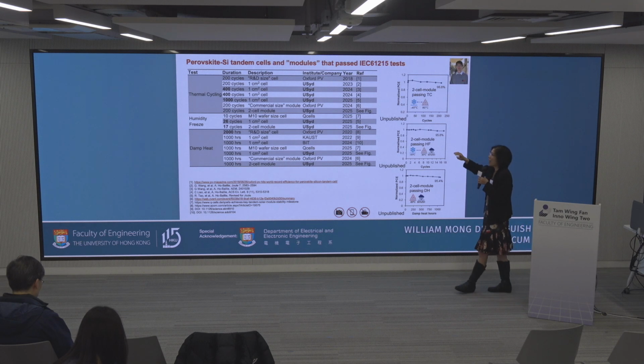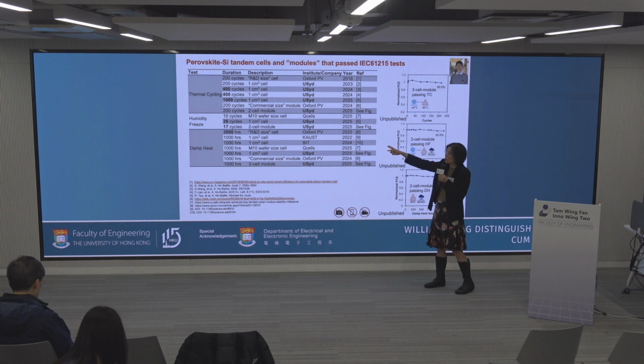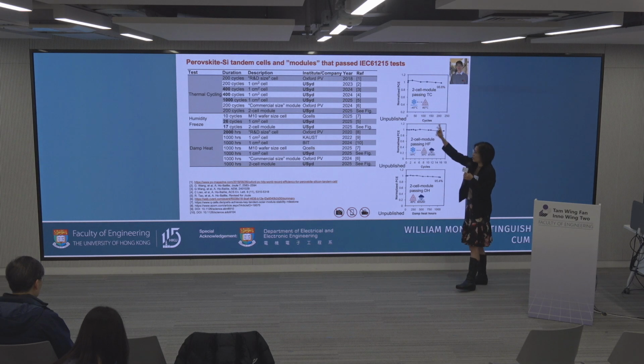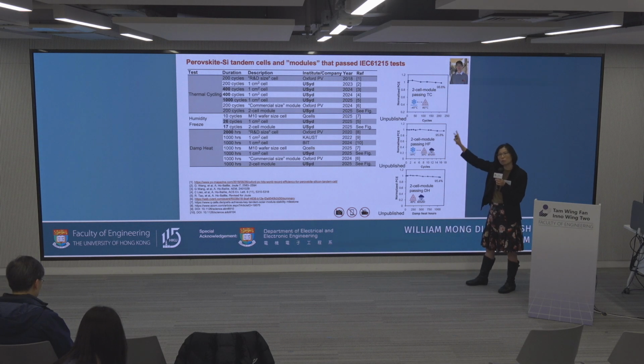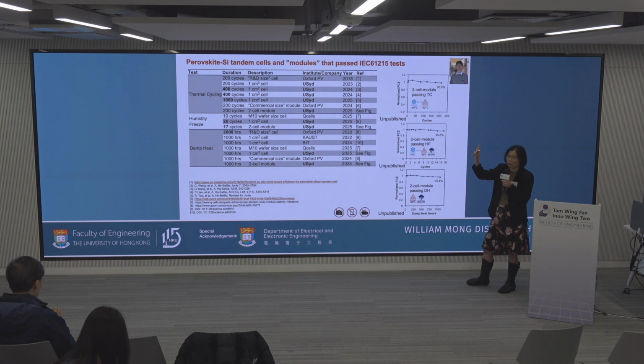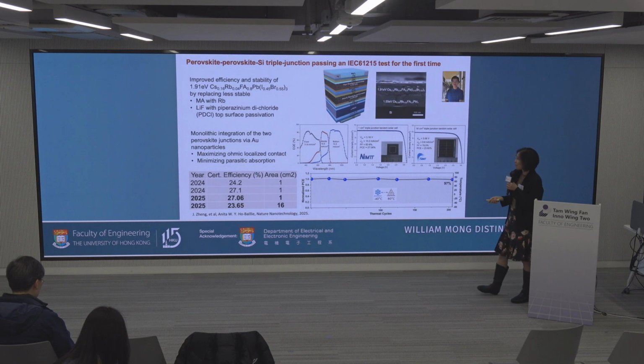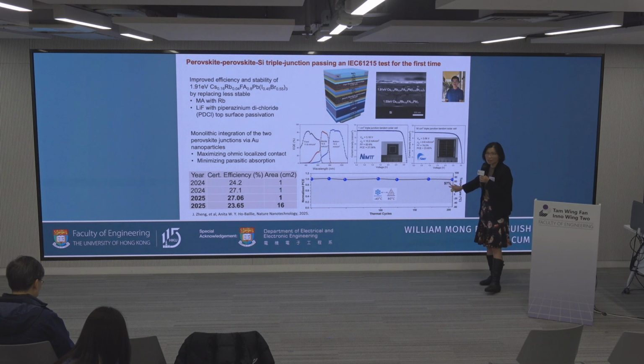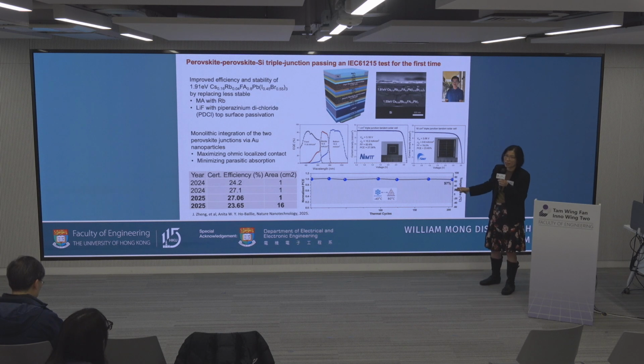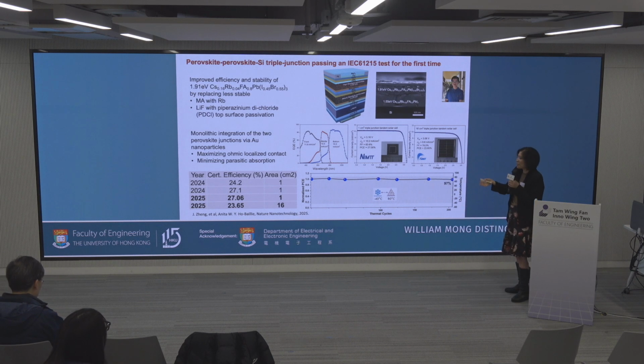So through this knowledge, we apply it for tandem. So these are all the tandem cell and tandem module stability as measured against the IEC thermal cycling, humidity freeze, and damp heat standard. And you can see, there are around 5 groups in the world that are just looking at tandem for passing IEC tests. Okay, so we also use that knowledge to look at triple junction. So this is the very first triple junction that passed an IEC test, and also we apply it for large areas. So at the time of reporting, that's the largest area cell, and therefore that's the most efficient large area triple junction.